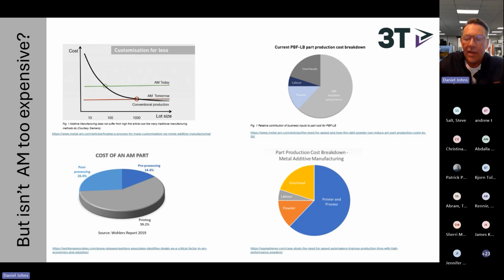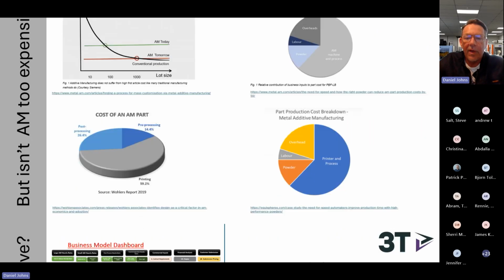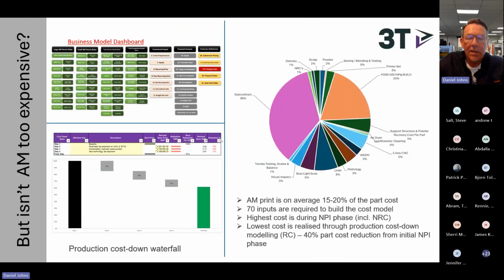If you look at it on a value chain level, which we can do because we have all the processes in-house, this is an example from our dashboard to create the cost base from a pricing perspective when we respond to an RFQ. This particular one is based on an M290, which is one of the slower machines, so it's probably the worst case. With the multi-lasers, it gets better. But in this case, 20% is the printing. You'll note as well that powder is only 2%, so even that's not as high as you might see. The big part is the subcontract, in this case CT scan.